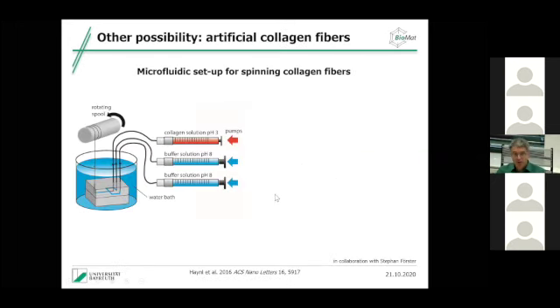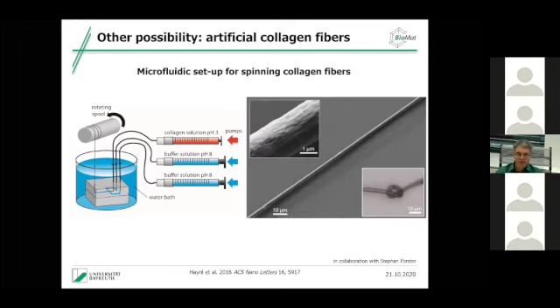We also can use collagens for that. And this is a technology that we developed a few years ago, a microfluidic setup for spinning collagen fibers. I wanted to show that to you because this is a very unique technique to make endless collagen fibers with unique properties. All you need is collagen solved at a slightly acidic pH. You have 2 neutralizing solutions, and then you have the setup where the collagen solution is not getting in contact with the wall of this fluidic channel. And then you can make fibers like that endlessly.